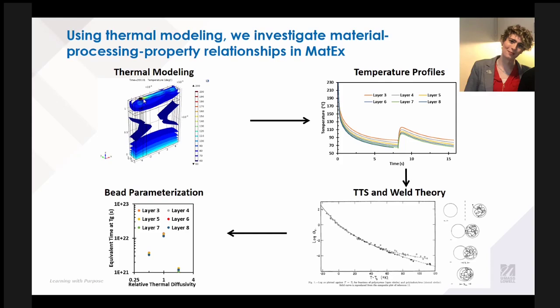You can see that it's hotter immediately behind that nozzle where material has just been extruded. So our approach is to develop these thermal models, and from these models we get temperature profiles. We get a lot of time temperature information, which is really interesting but a little cumbersome to deal with. And so from there we take advantage of time temperature superposition and polymer weld theory in order to condense that information down to a single number that can give us information about the predicted mechanical properties of these structures.